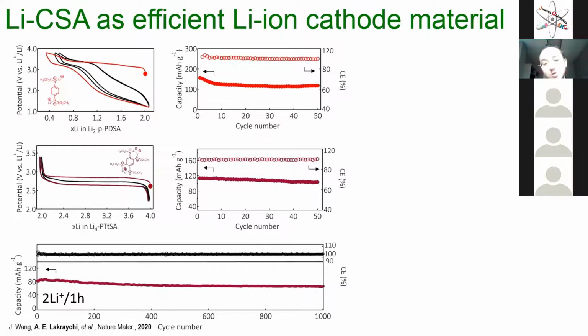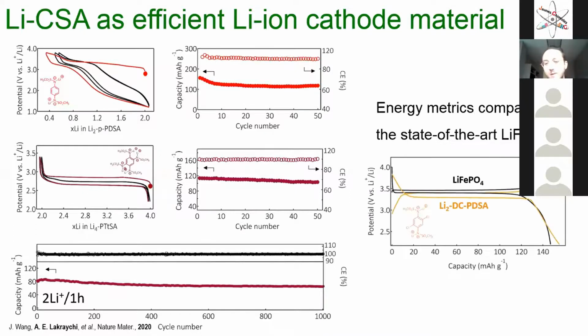So you are going to see some nice work on this molecule in the literature very soon. And the second thing is that one of those molecules actually can be comparable to the state of the art, which is lithium iron phosphate, in terms of energy metrics. So the energy metrics are the voltage and capacity. This one can provide the same capacity, pretty much the same voltage, but it suffers from stability. We are working to have this stable during cycling, and then we will see if we can make some electrodes with the same mass loading as compared to the LFP. But this remains a big advance on the lithium-containing cathode material.